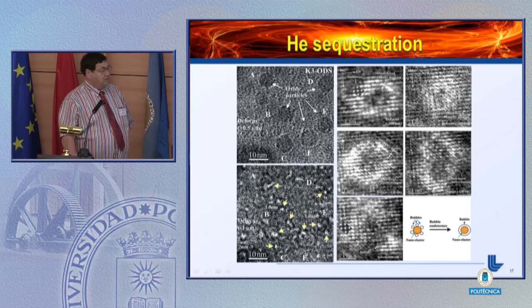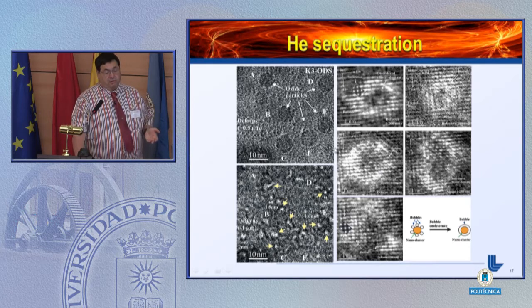It turns out that the process of ball milling or mechanical alloying, followed by consolidation, not only results in these obvious recrystallized particles, but it apparently also produces a large amount, actually an order of magnitude more, of particles that are so submicroscopic that they can't be observed in normal 3D atom probe or high-resolution TEM microscopy. Somewhat analogous to biological staining, the helium makes it evident. And so this tells us now what the manufacturing process for ODS materials should be in the future to get the optimal management of the helium effect that ultimately leads to unconstrained cavity growth and dimensional changes.